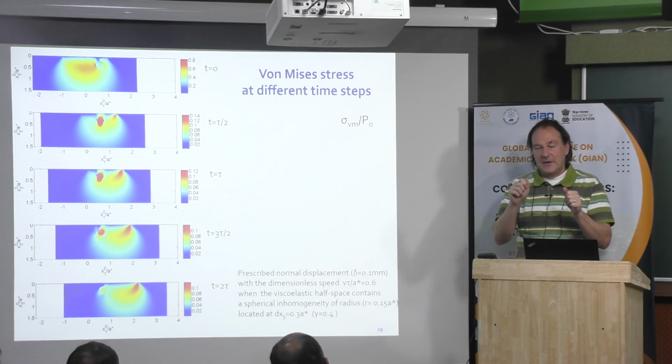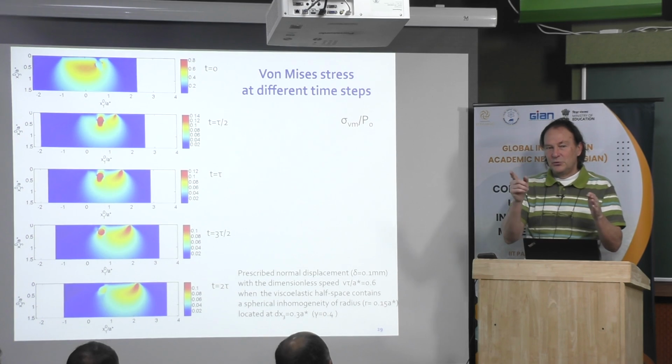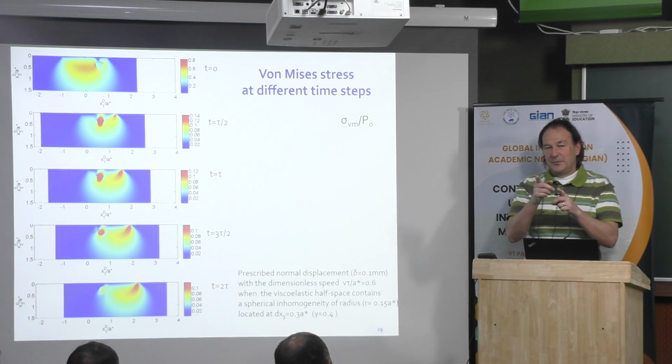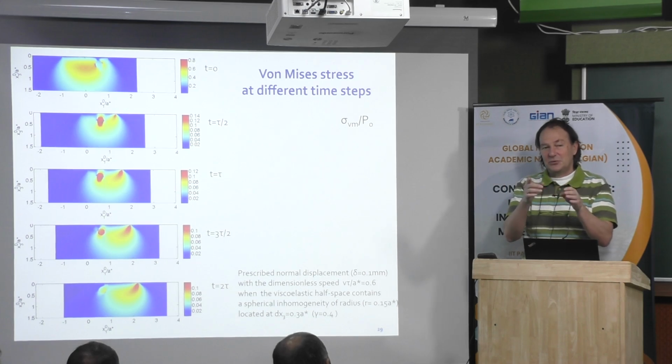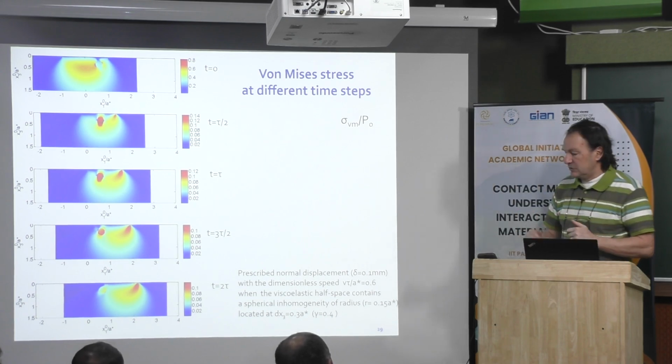It's very difficult. Now, if you do that for a polymeric bearing, you have to be careful because if you use a distance, when you mount the bearing, the load will be very high and it will relax and the load will decrease. When you use a spring, you will have a constant load. Okay, just a small remark.